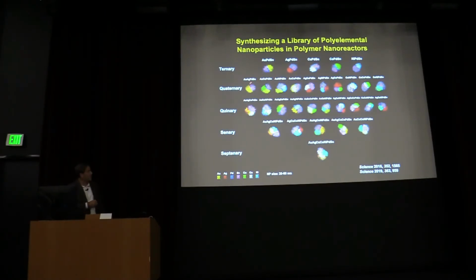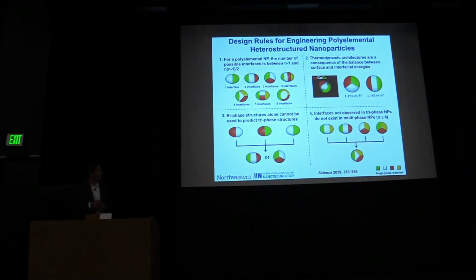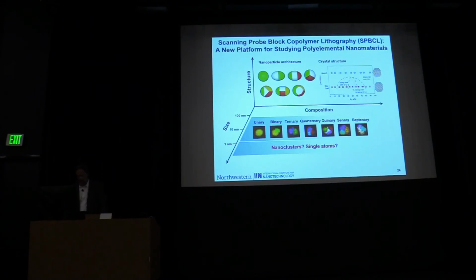But he went through and characterized all the phase behavior here and the interfaces that form. Nobody knows how these types of structures are going to behave. Well, we can do that. And if you're interested in this, we actually went through the full analysis. And you can begin to create design rules for making these types of polyelemental systems, where you can design interfaces, both the number of interfaces, the types of interfaces. You can dictate it by an understanding of interfacial energies. And as you begin to study the hierarchy, going from 2-phase, 3-phase, 4-phase, 5-phase, or 2-element, 3-element, 4-element, 5-element type systems, you can begin to create rules that allow you to predict what the next set of structures will do. And so I think there's going to be incredible value added in terms of fundamental understanding with respect to polyelemental systems that come from these tools.